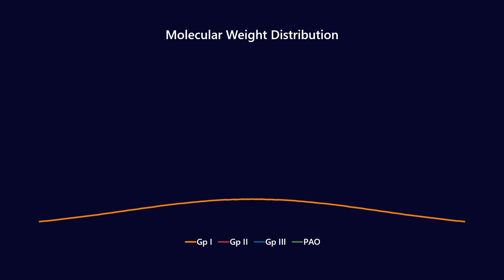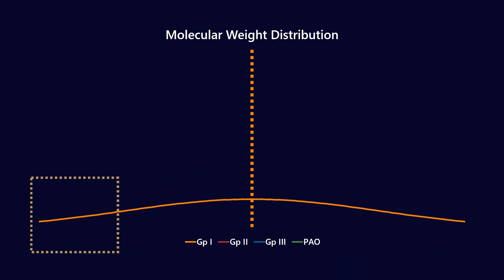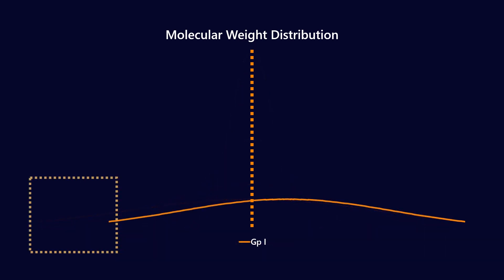In terms of how flashpoint changes as a lubricant decomposes — looking at the molecular weight distribution of a Group I base oil, you have heavy ends at the top and light ends at the lower range. Over time, as the lubricant volatilizes, the light ends disappear and the distribution shifts toward higher molecular weights. This happens much more in a Group I than in a PAO, because Group I has far more light ends. This shift also causes the lubricant's viscosity to increase.